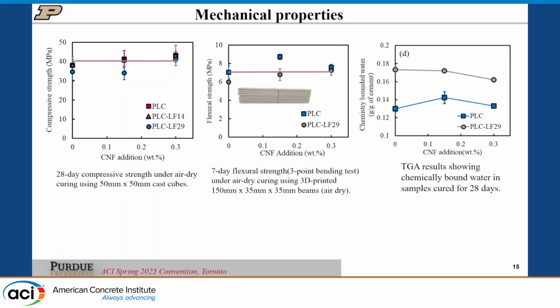We also wanted to make sure we're not sacrificing mechanical properties, so we measured compressive strength and flexural strength. Compressive strength was measured with cast specimens, whereas flexural strength was measured with printed specimens, because we know there are fiber alignment effects that happen with 3D printing, and we wanted to see if this would translate to nanofibers as well. What we see is some increases in compressive strength, which aligns with the literature, but for flexure we did not see a significant increase. So we did not anticipate the same fiber alignment effect with 3D printing that we see with microfibers.